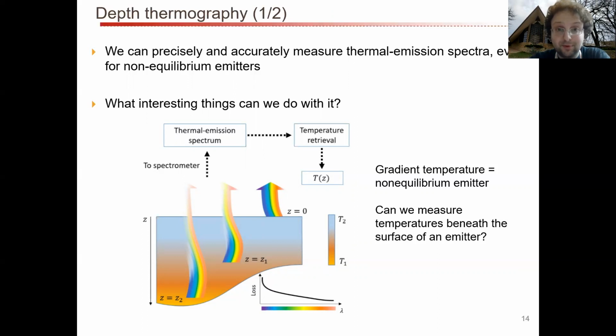Using this very precise method of measuring thermal emission spectra, we can in certain cases, for certain materials, peer underneath objects and try to measure the temperature as a function of depth. So here's an example of how something like this might work. If you have an object which has, let's say, a flat surface here, it doesn't necessarily have to be, and it has some loss which is a function of wavelength, then that affects, when you're doing a thermal emission measurement up here, where the thermal emission signal is coming from, right?